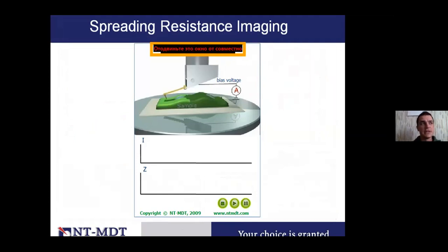One of the interesting techniques is called spreading resistance, and it's used to study the conductive properties of the sample. The idea of this technique is that we use a conductive probe, we use a conductive sample, and we ground the sample and apply some voltage to the tip. Depending on the conductivity of the surface, we can measure the current. We can measure the current at a single point or at some grid, or we can do the scanning, XY mapping, and at every point we will measure the current. So finally, we will get the distribution of the current with a constant voltage applied between tip and sample.